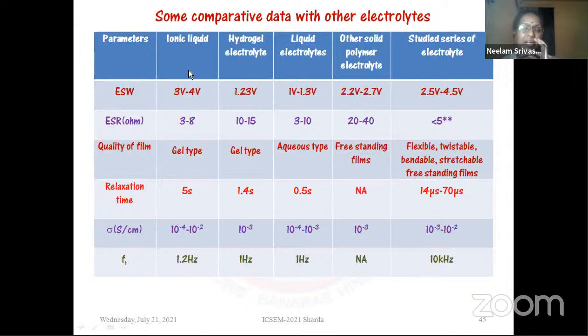For ESR value, with the ionic liquid it has been reported as 3 to 8, and for other systems it is even higher. For our system it is less than 5 ohms. So again, good result. Compared with ionic liquids and gel electrolyte, our system is flexible. It can be twisted, bent, stretched, everything. So it is good again. The relaxation time, which is in seconds for others, we are getting in microseconds, again a good thing. Conductivity is also very good if you compare with all. And resonance frequency is very high. That is a very important thing, because resonance frequency puts an upper limit to your system.